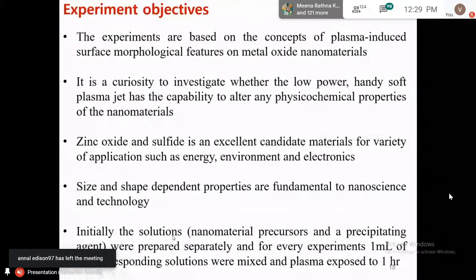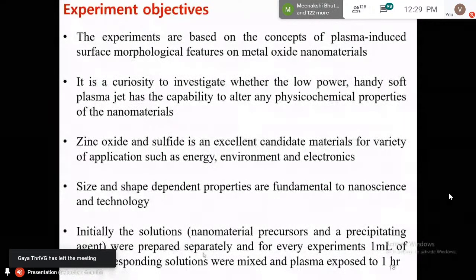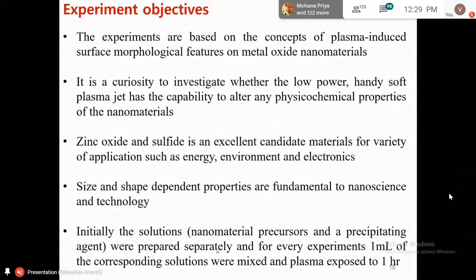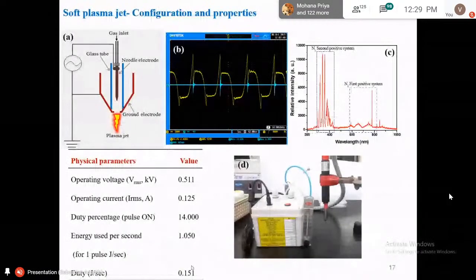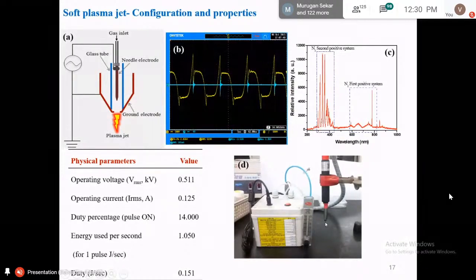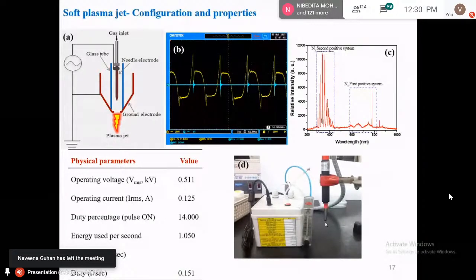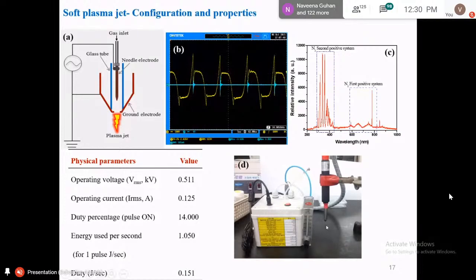Initially the solutions, that is the nanomaterial precursors, were prepared separately, and 1 ml of the corresponding solutions were mixed and exposed to plasma. So this is the plasma system. The plasma comes out here. Suppose we want to prepare zinc oxide, we have to take zinc precursors such as zinc nitrate, chloride, sulfate or acetate, and then one precipitating agent, NaOH or ammonium hydroxide, anything, in a bottle, mix it, and then expose to plasma for some time.